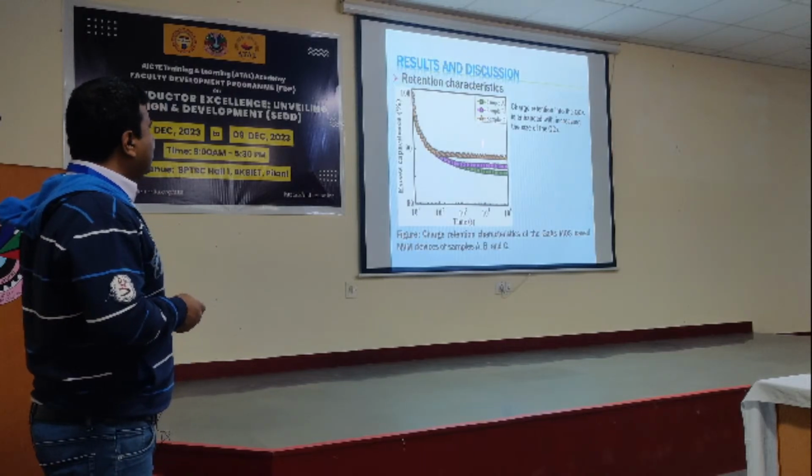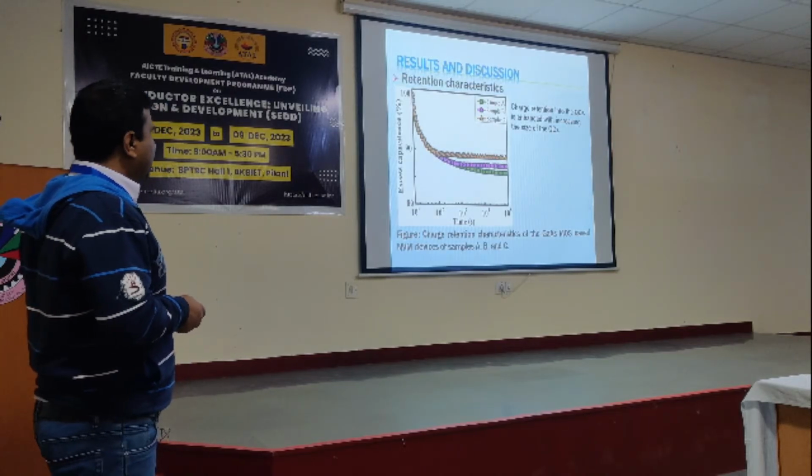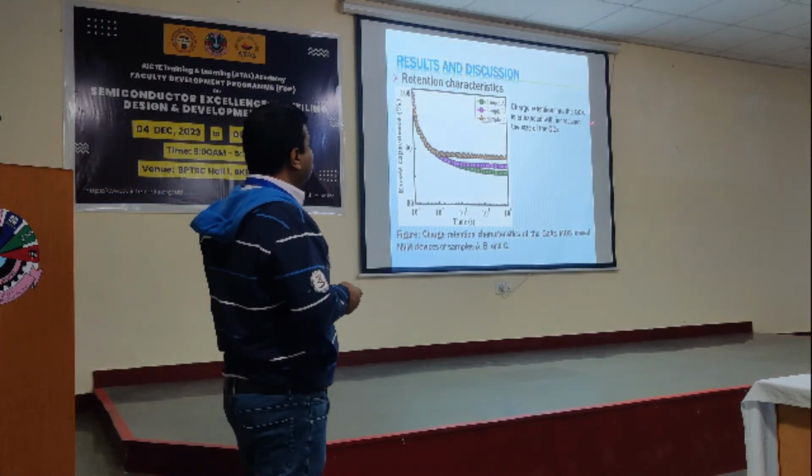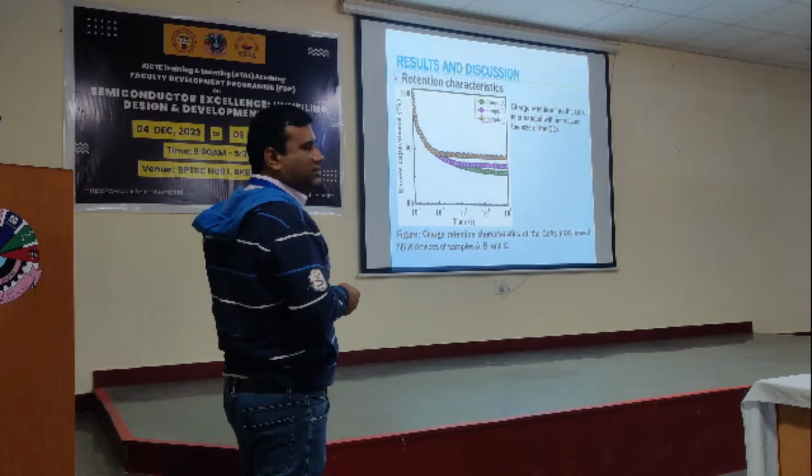Now again, for all the cases you can see here the charge retention taking place for all the devices, from 5 to 16.5 nanometers. Charge retention in the quantum dot is enhanced with increasing the size of the quantum dots.